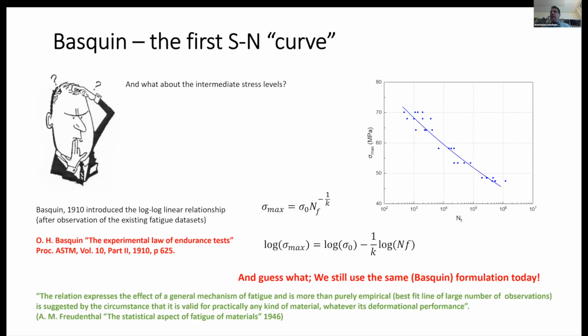We still use the same equation today. This is the basic SN curve equation that we are using even today for composite materials and even for metallic materials. Although it is a fitting equation that can be estimated by linear regression, it has some physical meaning. This is reported in a paper from Freudenthal in 1946. You can read that the relation expresses the effect of a general mechanism of fatigue and is more than purely empirical, which is the best fit. It is suggested by the circumstance that it is valid for practically any kind of material, whatever its deformation performance. So it has some basic physical background.